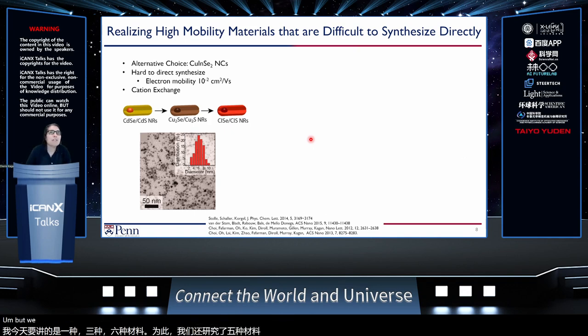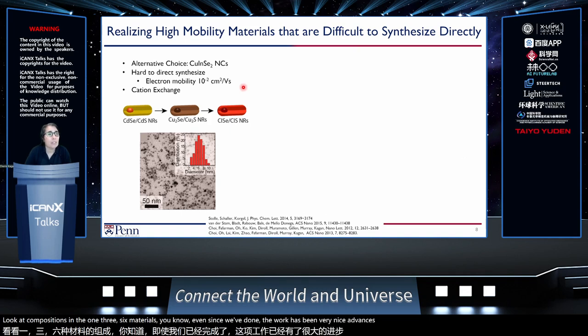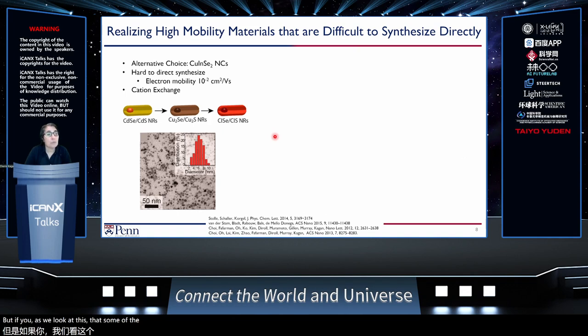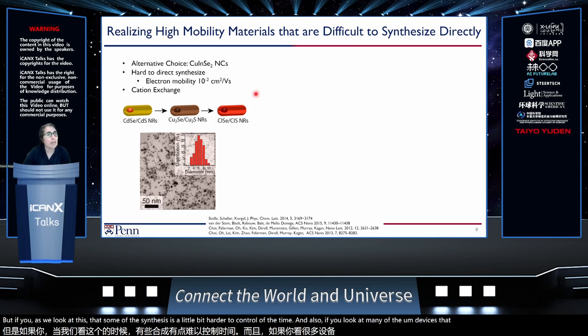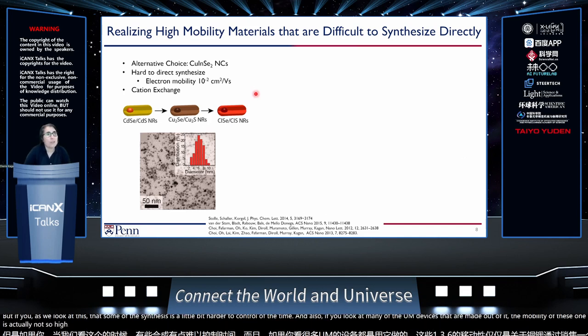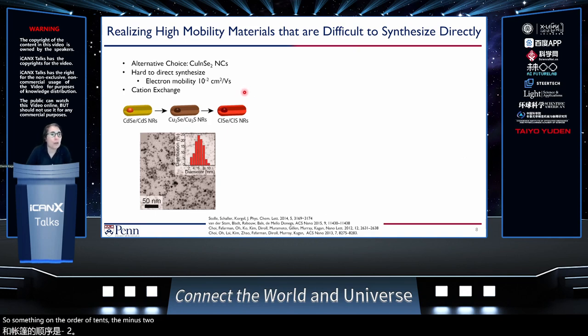But we had looked at the time at the challenge of how we look at compositions, and the 1-3-6 materials, even since we've done the work, there's been very nice advances in their synthesis. But as we looked at this, some of the synthesis was a little bit harder to control at the time. And also, if you look at many of the devices made out of it, the mobilities of these 1-3-6 materials, I'm going to tell you about copper indium diselenide in particular, is actually not so high, something on the order of 10 to the minus 2 centimeters squared per volt second.